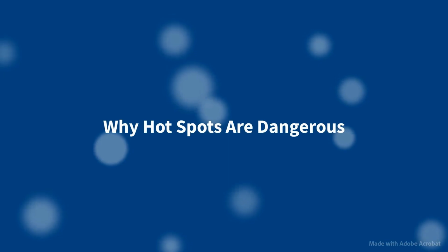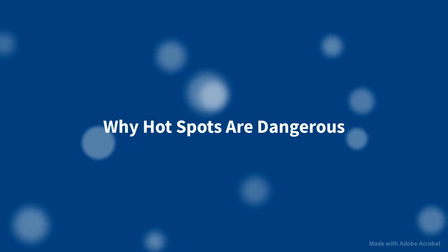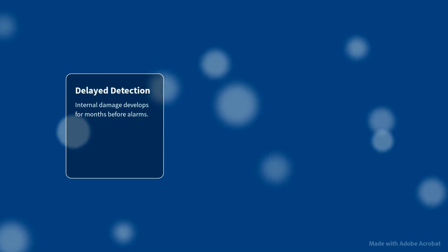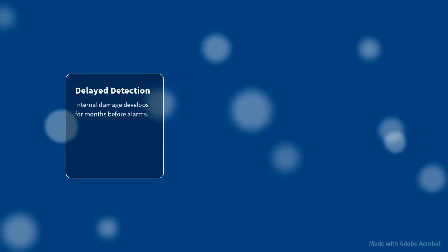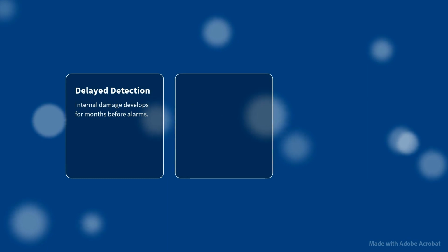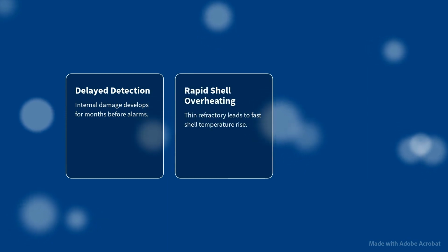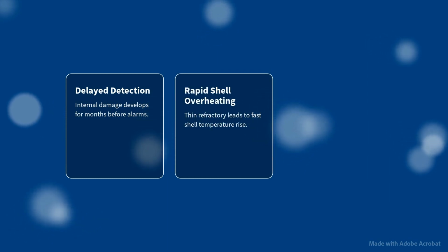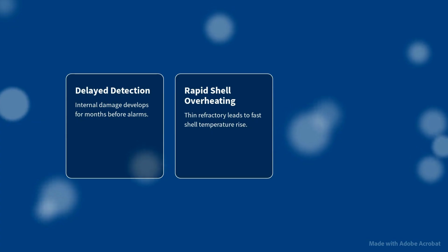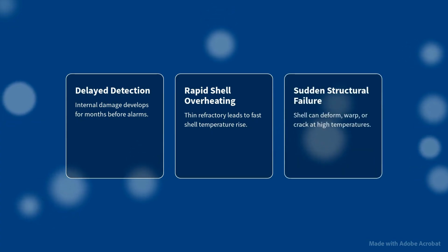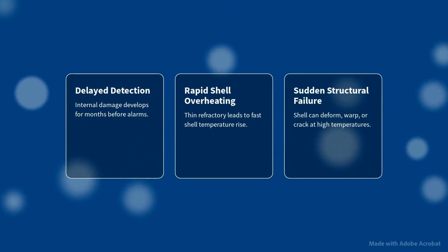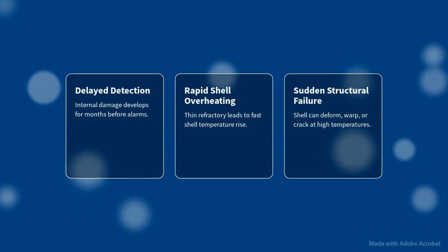Now, let's look at why hotspots are so dangerous and why they can't be ignored. Delayed detection means that internal damage can develop for weeks or months before any alarms are triggered. Rapid shell overheating occurs once the refractory becomes too thin, causing the shell temperature to rise quickly. Sudden structural failure is a real risk, as the shell can deform, warp, or even crack when exposed to high temperatures.